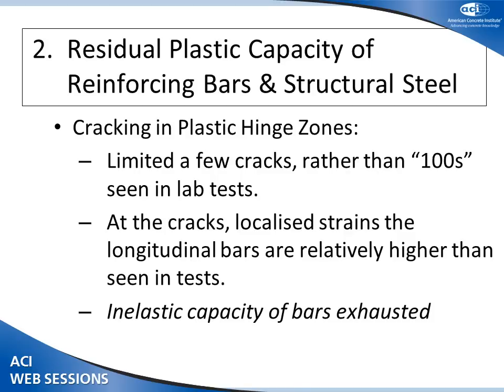Now, from laboratory work that goes back before even we were students, you'd say under multiple inelastic cycles, you would get yield penetration, bond failure along the bars, anything from 2 to 4 bar diameters either side of the crack. This is partly to do with the loading scheme that most laboratories have used over the years, which is to progressively deform your column or your beam more and more. This has led, we think, to progressive bond breakdown and a reasonable length of bar either side of a crack